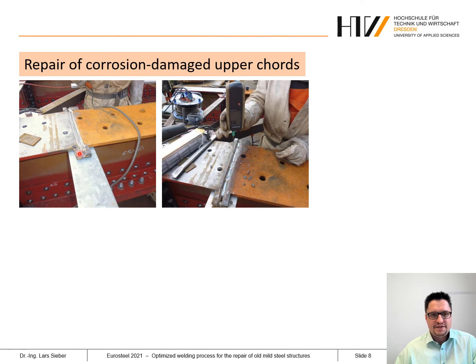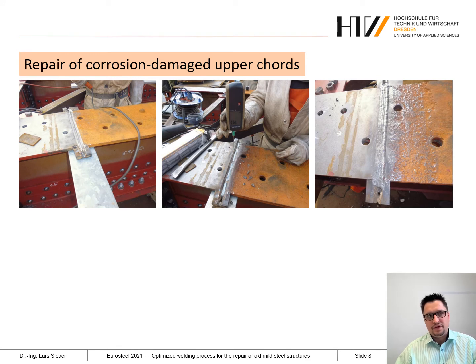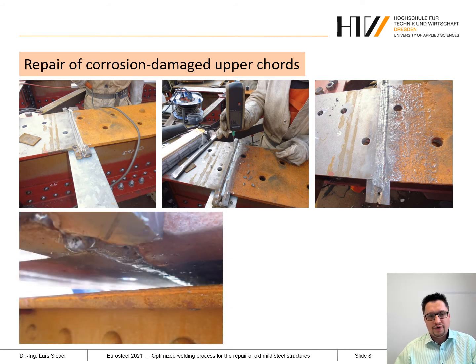As you can see here, the adjacent rivets were removed to be able to lift the chord plate and to be able to use a ceramic welding backing for the root weld, because we were not able to weld in a double groove like in the other experiments. As you can see, the groove here was welded by stringer beads, in one direction, and also in flat position. Here, the welder checks the interpass temperature to minimize the heat input into the material and to avoid the coarse grain formation. And finally, after cutting the welded ends, the plates were bolted to the upper chord of this structure.